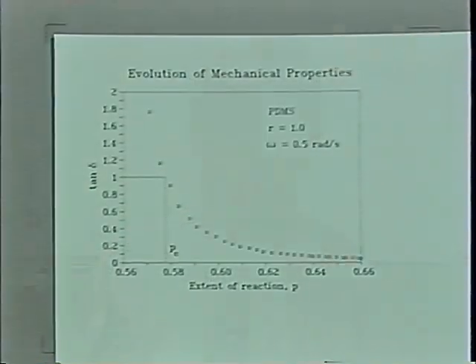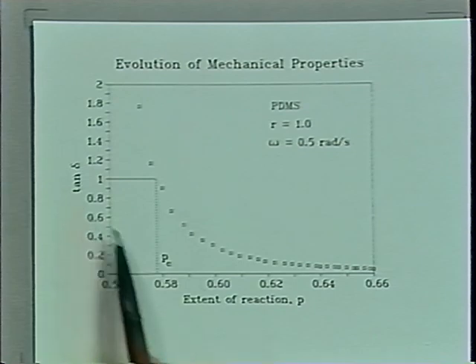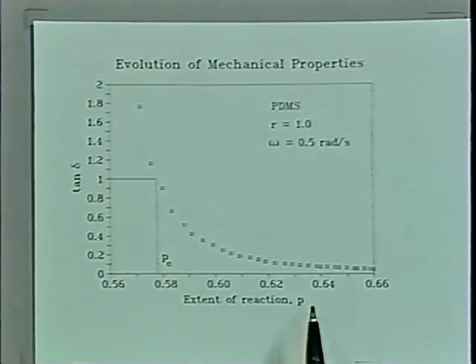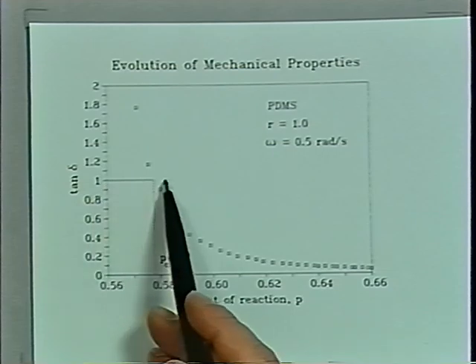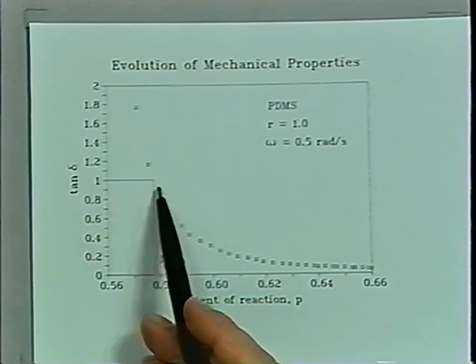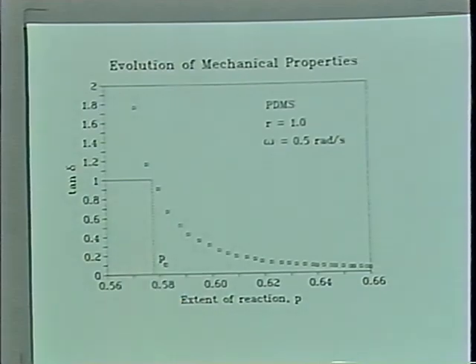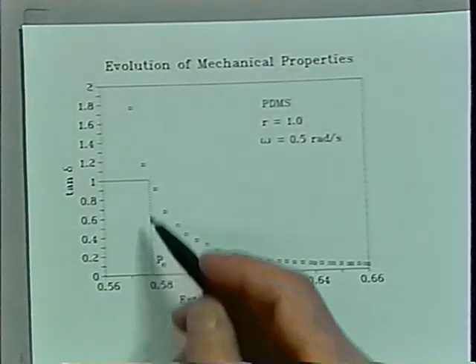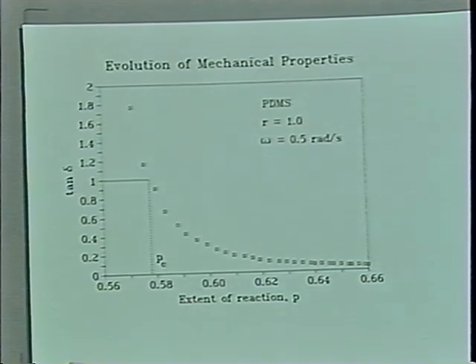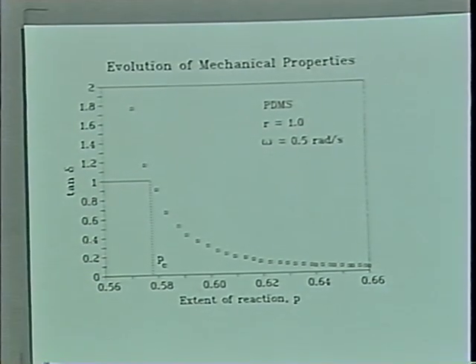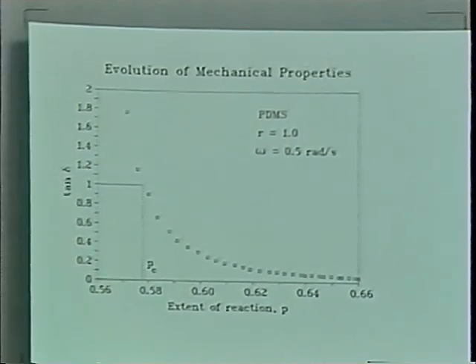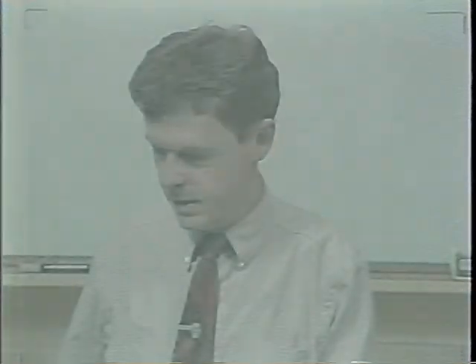The conversion can be measured with optical techniques. We do that with Raman, for instance. This would be now tan delta measured at a set of different conversions. From rheology, we learn tan delta coming in here. This is for this sample where tan delta was equal to 1, and the conversion was close to 0.57, which in this case we would have a prediction of 0.57 having a difunctional and a trifunctional system reacting.